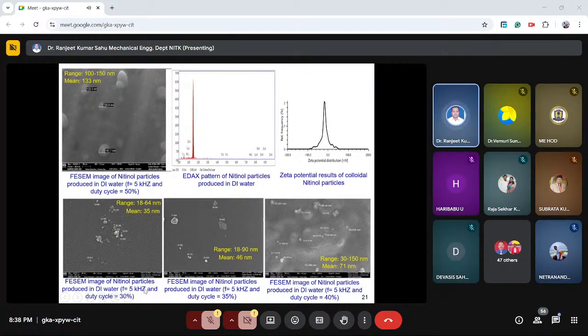Then what happened? We have just changed the duty cycle. When the duty cycle reached 30%, the mean size reduced to 35 nanometer. That indicates that when the pulse duration is very small, we are able to remove the material at a very low scale. That means low unit removal of material takes place, and we are able to achieve 35 nanometer in the vacuum atmosphere, and also with a cold environment at a temperature of 4 to 5 degrees Celsius.